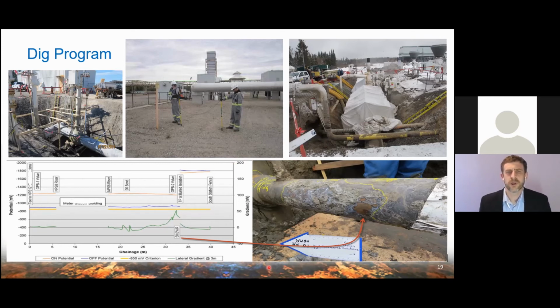Now here, I just want to draw your attention to this data here. This was in that first station that we did. And we had a nice big coating defect. Well, nice big. Very satisfying to find it in the field, although of course, that's not what anybody wants to have on their piping. So kind of competing priorities in terms of who wants to see what. But we had this coating defect. It was fully protected, so we didn't expect to see any corrosion. It wasn't at a valve, so we were really interested to see what it looked like. Dug it up, and yeah, it was confirmed. There was quite significant coating damage in this area here.